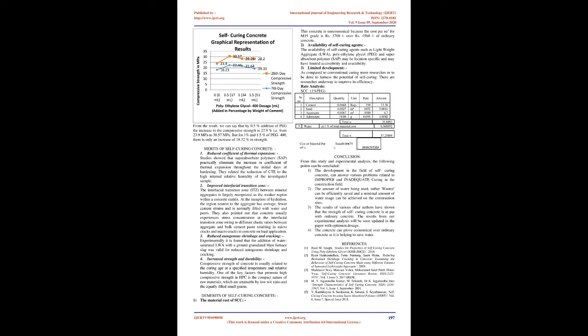The amount of water added to fresh concrete is one of the most important key factors affecting concrete properties, including durability and strength. Water is needed for the hydration process in fresh concrete and the curing process in hardened concrete at its early stages. Principle of Self-Curing: Proper curing of concrete structures is important to meet performance and durability requirements. Self-curing or internal curing is a technique in which additional moisture is provided in concrete — not a part of mixing — for more effective hydration of cement and to reduce self-desiccation. Mechanism: Continuous evaporation of moisture takes place from an exposed surface due to the difference in chemical potentials (free energy) between the vapor and liquid phases. The polymers added in the mix mainly form hydrogen bonds with water molecules and reduce the chemical potential of the molecules, which in turn reduces vapor pressure, thus reducing the rate of evaporation from the surface.